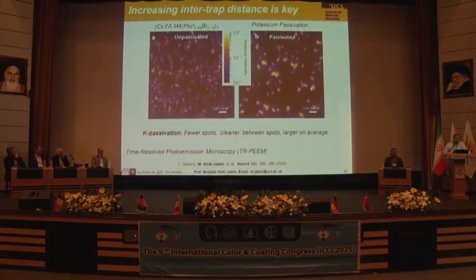We also look at the distribution of defects within the perovskite thin film. This is a very advanced measurement technique called time-resolved photoemission microscopy, where you can locate the defects within your semiconductor. You can see on the left-hand side a lot of defects within the thin film. When we passivate it, you minimize the number of defects, and you have less of the green spotlight, or orangish spotlight.